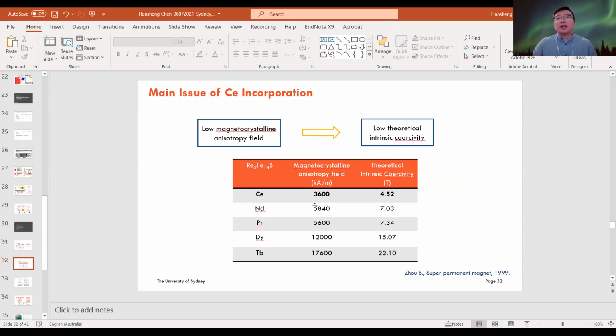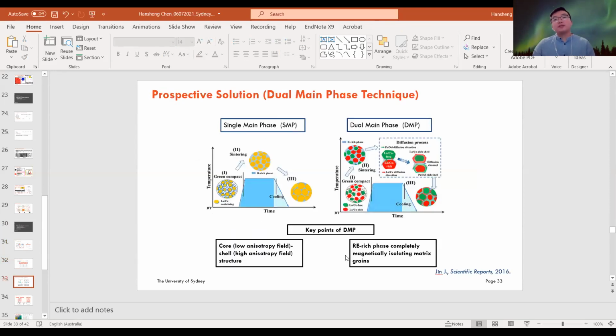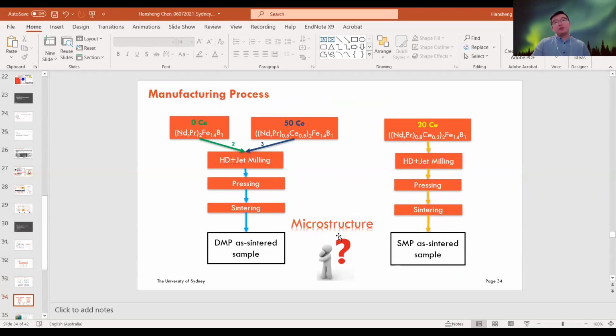But the reason is, you can see, if you're using the cerium as the base for these 2:14:1 phases, the anisotropy field, which is directly related to the intrinsic coercivity, is halved. Then we would like to balance the incorporation of the cerium here. And one previous technique called dual phase is by constructing a so-called core-shell structure, which can majorly enhance the nucleation field, especially at the interface here. And here we would like to dig more into how the microstructure looks in this dual phase permanent magnet.